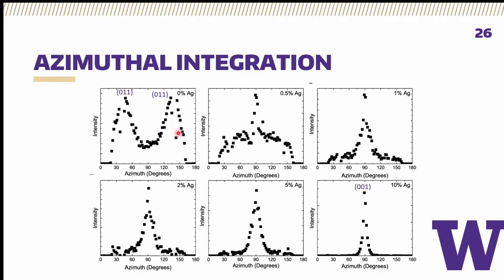It took a little bit of processing to filter some of the noise out, but this is much more illustrative. Based on where the X-ray intensity peaks along that azimuth, we have much more insight and don't have to rely on our deceiving eyes to figure out the orientations.